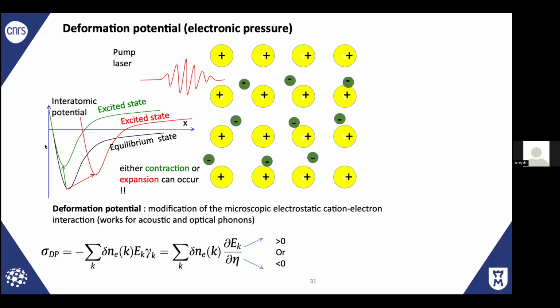So, yeah, for exciton, what is interesting is that you can really well control. If you are at quite low temperature, you can really well control the electronic level and populate this electronic level. After that, if you know exactly the deformation potential related to that level, then you should understand which phonon you emit. But again, the spectrum, you have to take care about that.